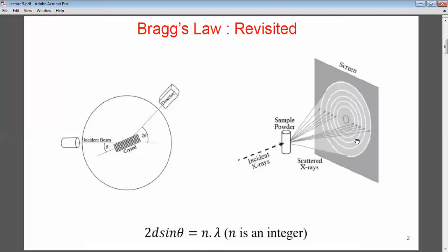When we irradiate a sample crystal with X-ray beams, the beams will get scattered by the electrons in the atoms that make up the crystal. The intensity of a diffracted beam will depend not only on the amount of scattering a single atom produces, but also on the scattering from the unit cell.